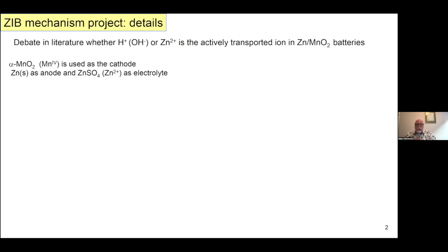So here we're using a particular phase of manganese dioxide, which has channels in it, tunnels, which are the appropriate size for zinc 2+ ions to enter. Zinc metal is used as the anode. Zinc sulfate is the transporter for the zinc 2+ ion in the electrolyte, and there's a separator to prevent shorting.